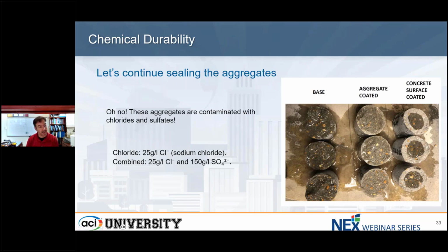And we see that has a profound impact on the wettability of that matrix. And then we looked at coating the surface, and you can see in this case, for this mix, the silane went about 3/4 of an inch into the surface because that part's not wettable and only the interior part's wettable.